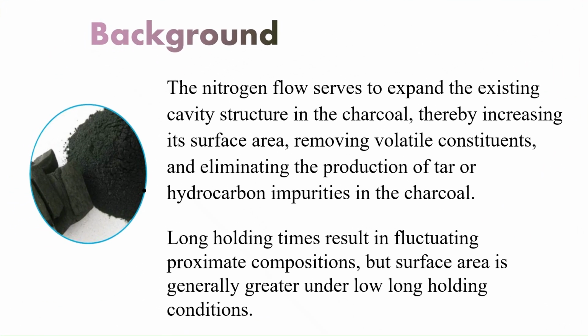Nitrogen gas plays an important role in preventing oxidation during activation, assisting in volatile removal, and supporting pore development. Holding time determines the extent of pore formation. Insufficient holding time results in underdeveloped pores, while excessive holding time may cause pore collapse and structural damage.